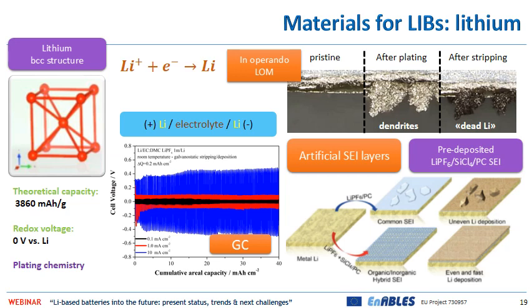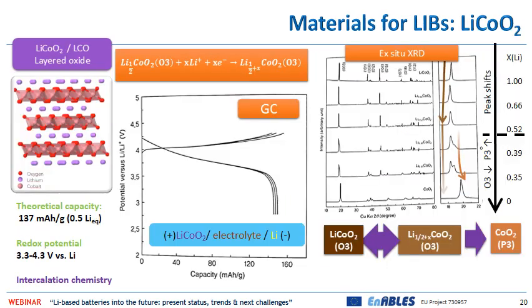This means that before assembling the material into the cell, it is possible to cast over the surface of the metal a blend of a polymer, lithium salts, and additives that forms an SEI layer that makes the penetration of solvent to the surface of the electrode less effective and thus prevents the degradation of the electrolytes over the surface of lithium. Let's tackle the positive electrode material.